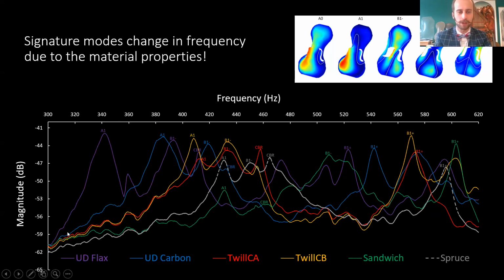The spruce top plate, we just added it as a reference. So it's around here. And then the sandwich material, which was, as you remember, very lightweight, 42 grams, and very stiff because it has the fibers in two directions. It has a lot of higher frequencies than the other violins. So here we see the A1 is the highest, the B1 minus is a lot higher than the other ones. And here also the B1 plus is slightly higher than that of the other instruments.